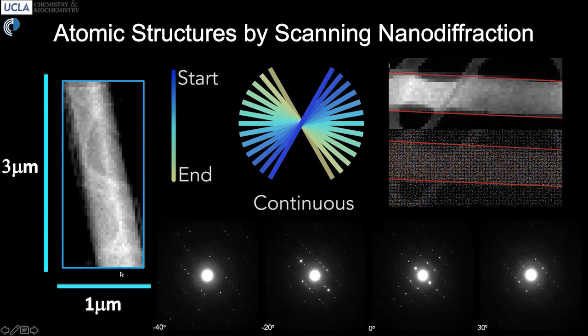So you can see the scan area here represents about 3 microns in the vertical dimension and 1 micron in the horizontal dimension. And this particular crystal is about 300 nanometers thick. And so we could scan that beam across that area. We could then parse out regions of our scans that we believe represented the core of that crystal, the part of the crystal that was diffracting best. And this was done ex post facto.